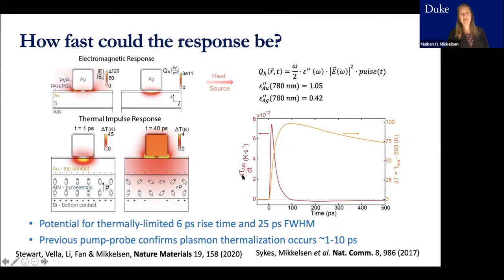And what we find is that it's the rate of temperature change here. So it's this spike here that gives us the response time. So if these simplified simulations can be believed, there's potential for much faster response times, potentially into the 6 picosecond rise time and 25 picosecond full width half max.